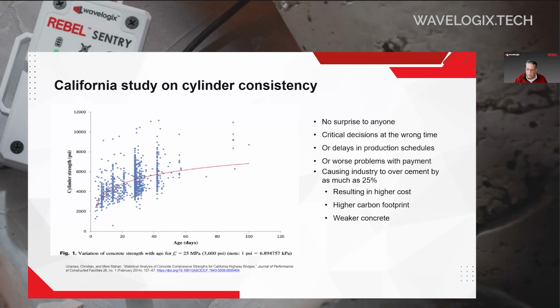A study was done in California, which I find really very interesting. This study on the graph shows the age of the concrete and the compressive strength of cylinders that were made. Each one of the blue dots is a cylinder that was crushed. The red line is the actual strength of the concrete at that point in time and showing its appropriate strength. Now, what's interesting is that California had 200 independent test technicians make cylinders from the same concrete mix over a period of months and then submit them for crushing, and then they recorded that. And the very interesting thing is that those blue dots are all over the map. There's almost a 500% error associated with some of those. And this is, again, what we're using every day to measure the strength of our concrete. So not the best process.